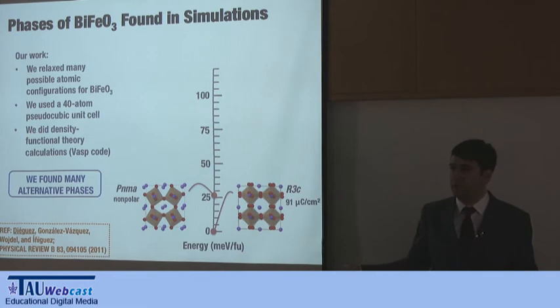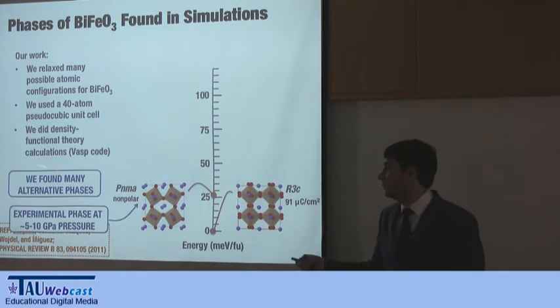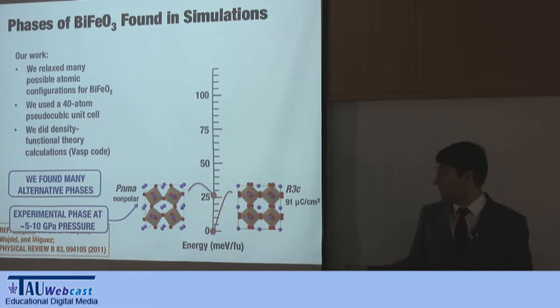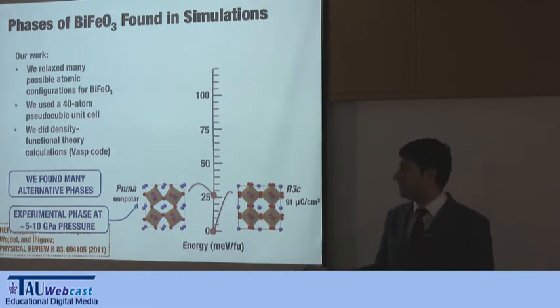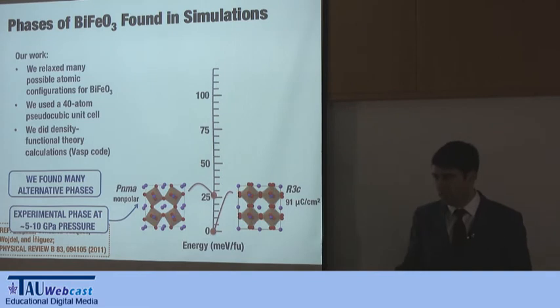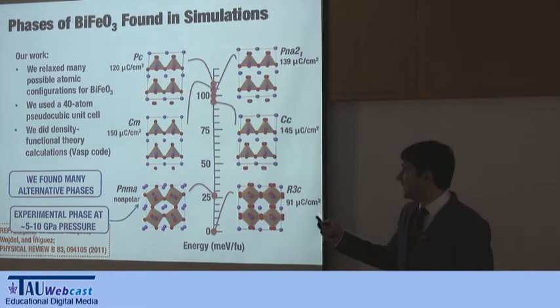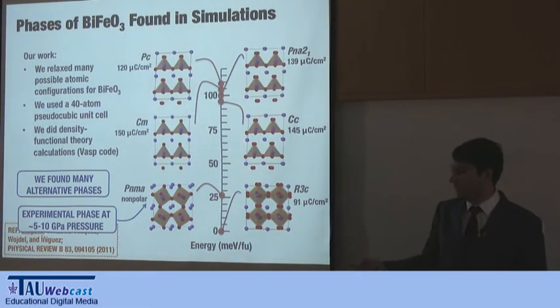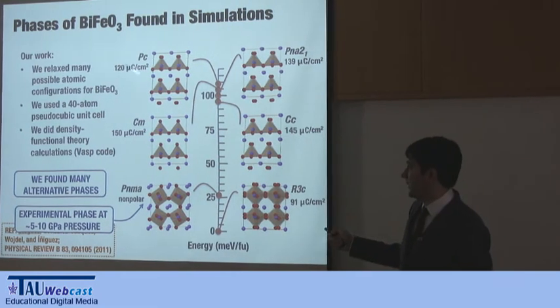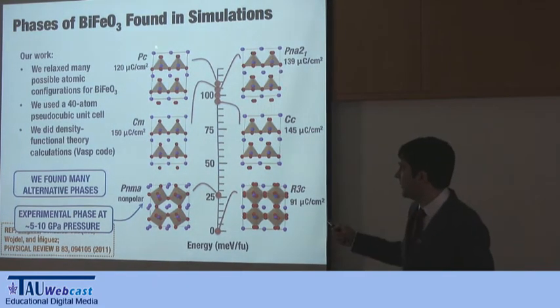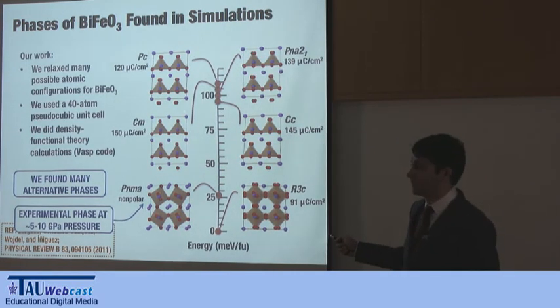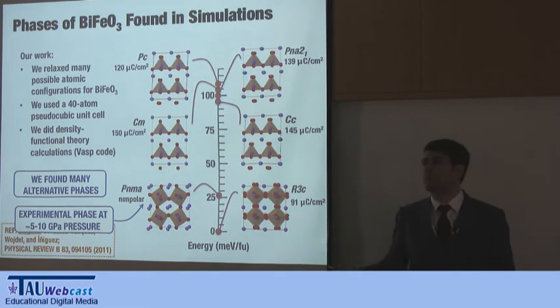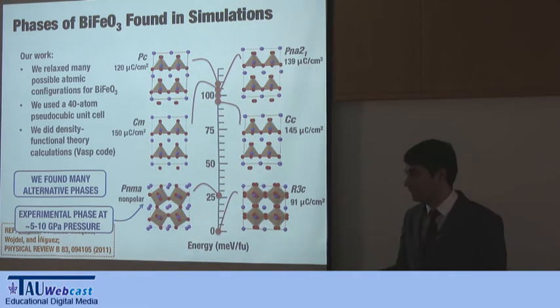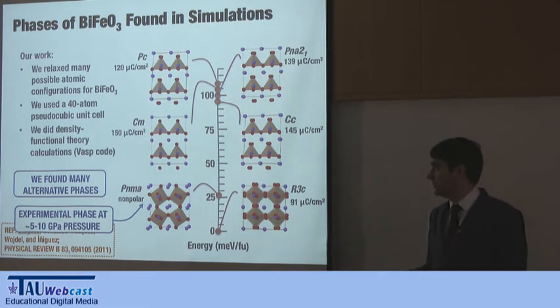Does it exist in the real material? It does exist when you go to high pressures. So this is the phase that the material takes experimentally at around somewhere between 5 and 10 gigapascals. What else is there? There are these so-called super tetragonal phases, because technically they are not tetragonal, but they have a very large ratio between this length and this one, the C/A ratio. So in perovskite it is around 1, and in this kind of thing it is around 1.3. Barium titanate is around 1.0304.